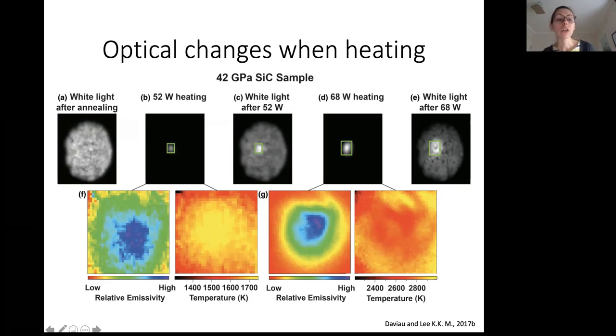And this is even clearer when we look at our emissivity and temperature maps. Down here, I'm showing maps of the thermal emission that was collected in these little green boxes during heating. At the lower temperatures, emissivity looks as we would expect, with higher emissivity in the center of the sample where it's getting hottest and the laser is focused, and this corresponds to higher temperatures in the center. So this is what we would expect. But at the higher temperature heating, the 68 watt heating, we again see high emissivity in the center, but the temperature map is different. Now we're beginning to see what appears to be lower temperatures in the center, which is not what we would expect and doesn't make sense with the emissivity map.